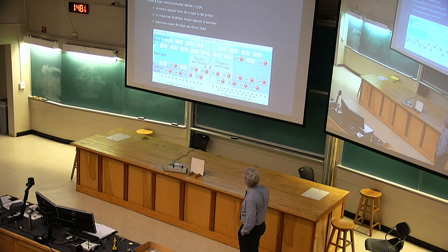And that building up of charge eventually stops the migration, because it's going to take too much energy to take these electrons out of this side, which is positively charged, and add them to this side, which is negatively charged. There's a repulsion that just says, no, you can't go. So the migration stops, and when it has, look at this central region.